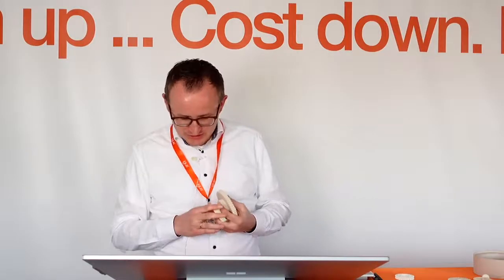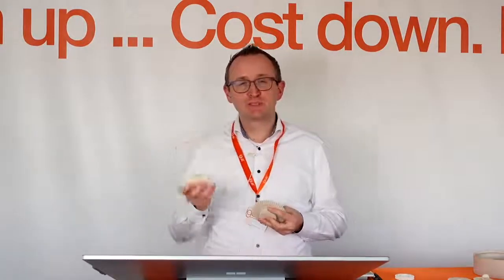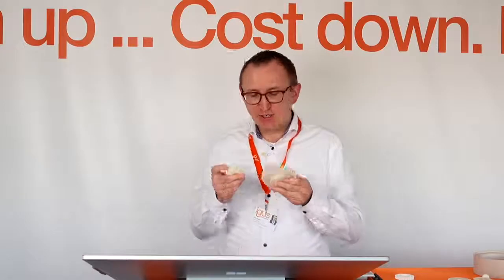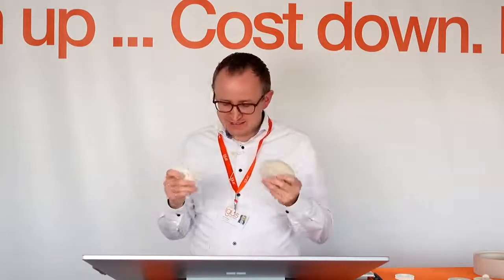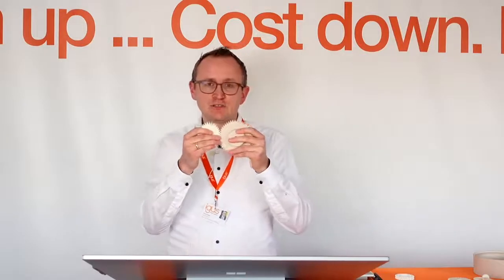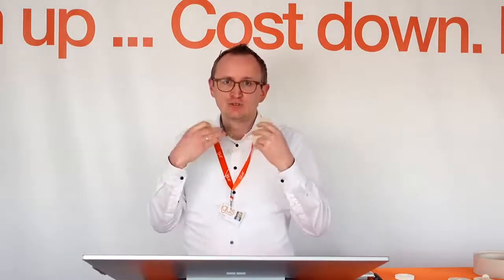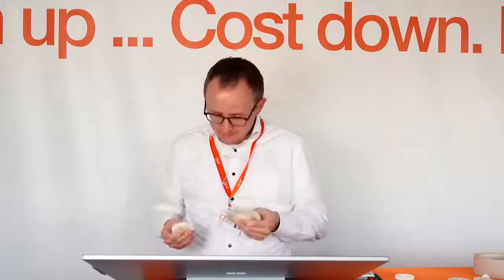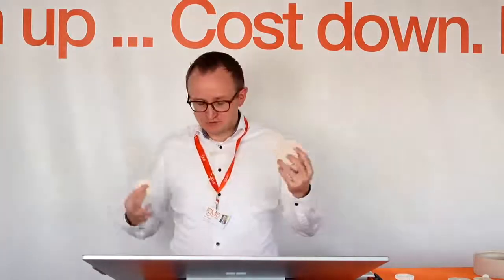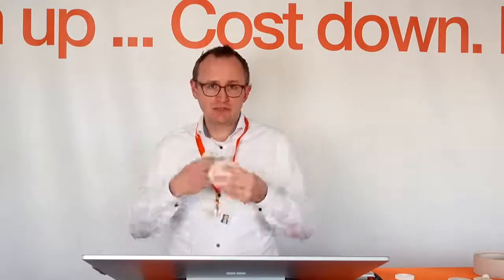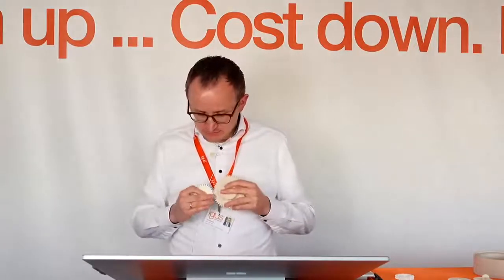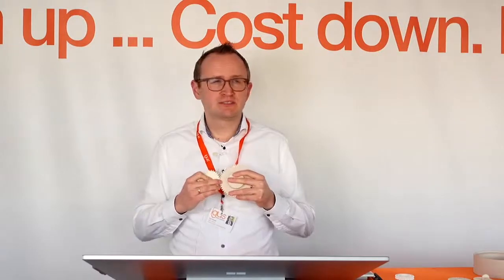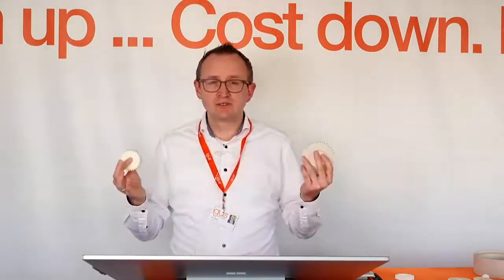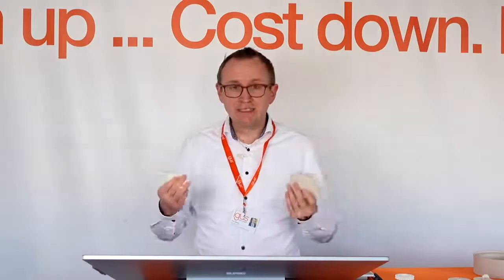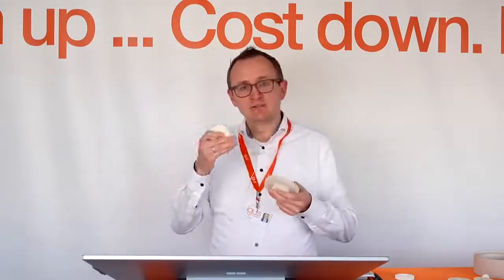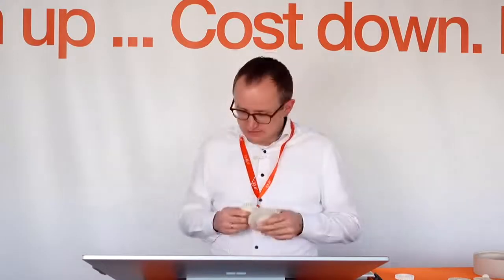Very good question. What type of grease to use with 3D printed gears? None, because the lubrication is already inside. At igus we put solid lubricants inside the plastic, so no external lubrication is needed. If, for some reason, you have lubrication in your system and cannot avoid it, most lubricants also work, but please don't hesitate to contact me or your igus contact to check the resistance of your oil against the printing material.